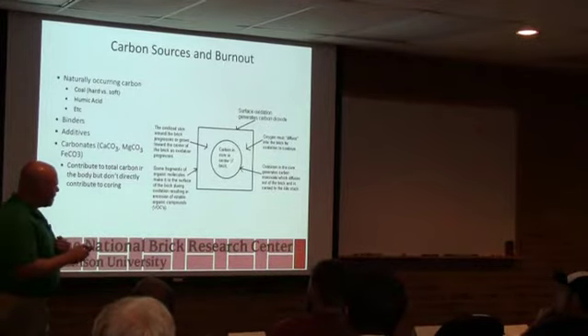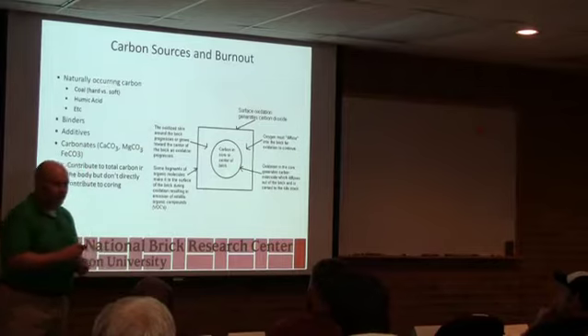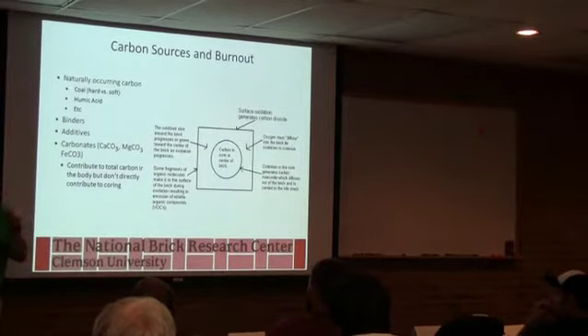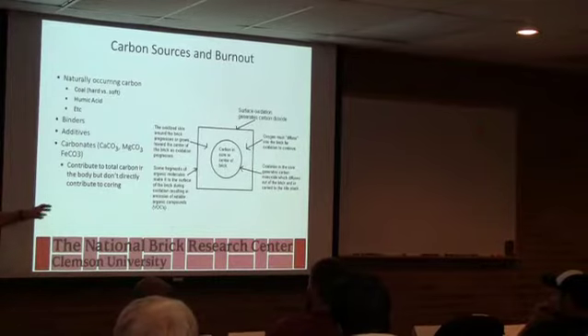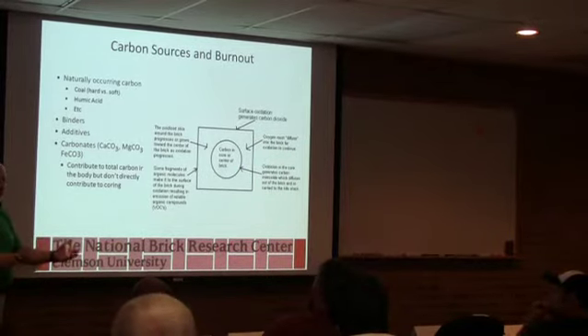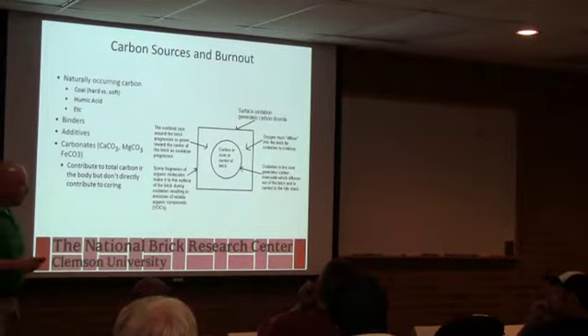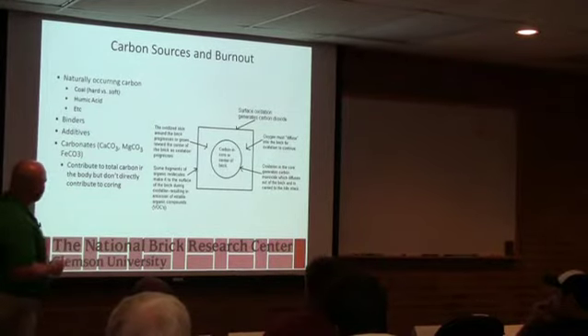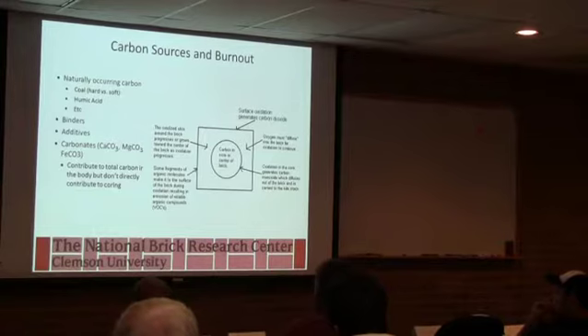One of the things we did with red body floor tile, in the tile industry, you're firing cold to cold in about 45 minutes. Okay, it's like a pizza oven, those roller hearths, and you don't have time to mess around with a black core. So we would add a little bit of manganese, MnO2, which gives off oxygen itself, and it would give oxygen in the body to help burn out that carbon. So there are tricks you can play on that.